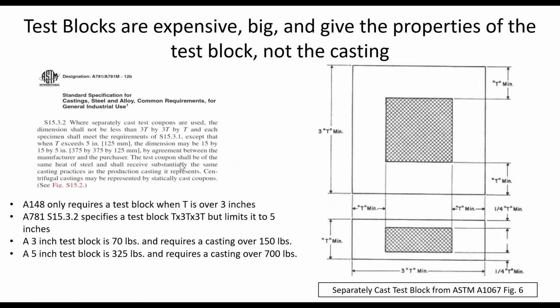Now, when I do that, when I call out S15, these test blocks are expensive. They get big fast, and they tell you what the properties are in the test block, not necessarily in the casting everywhere. And the S15 in paragraph 3.2 says when it's over 5 inches, you can just make it a 5-inch test block. So if you think about it, the A148 says if it's over 3 inches, I have to do a test block. But once it's over 5 inches, I use a 5-inch block. And that's because these things get big fast.